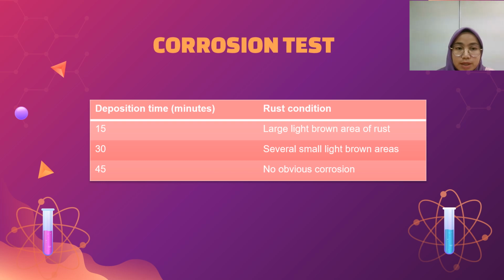For the corrosion test, it can be deduced that the higher the deposition time, the higher the corrosion resistance of the coated sample. For the sample coated for 15 minutes, there are large light brown areas of rust, while for 30 minutes, there are only several small light brown areas, and for 45 minutes, no obvious corrosion was observed.